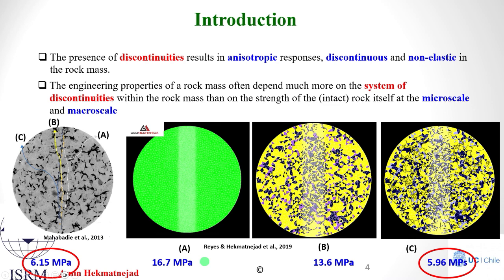In A, homogenization techniques were applied to capture the rock mass strain subjected to the Brazilian test. And you can see the result is 16.7 megapascal, which is quite far from the reality of the experimental test.